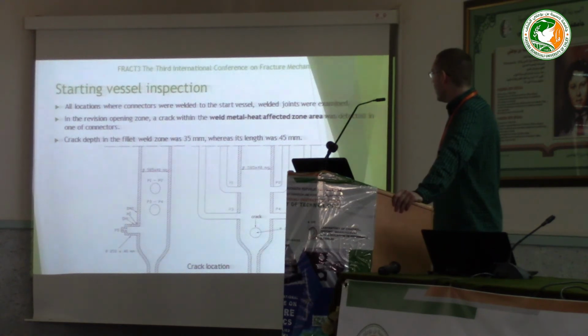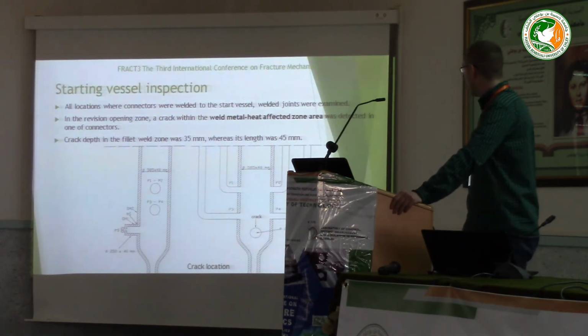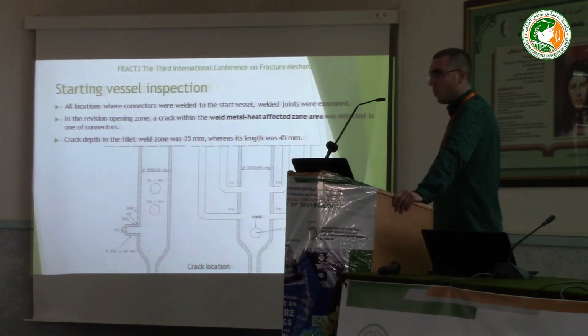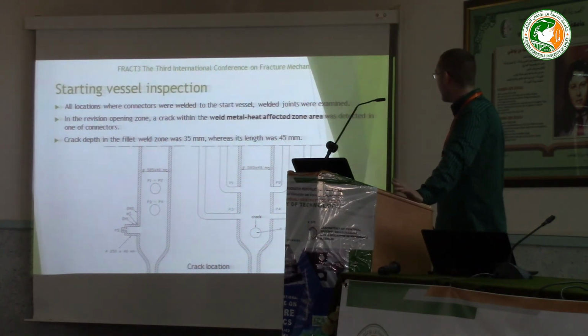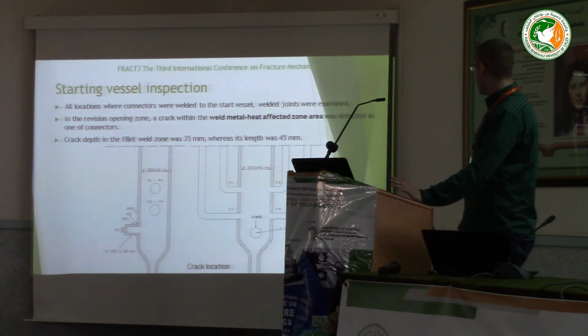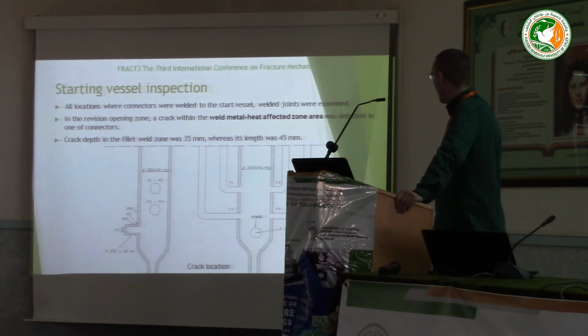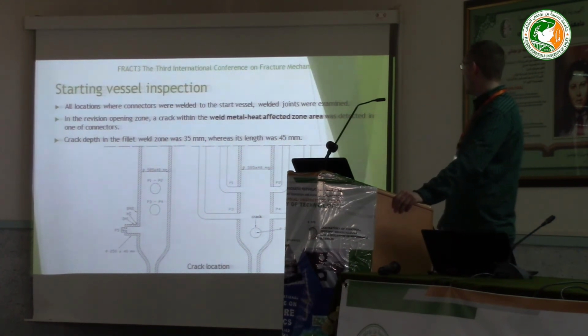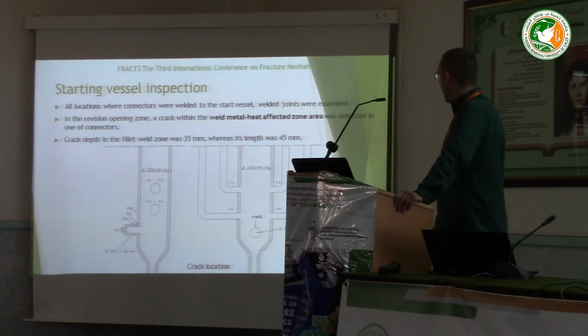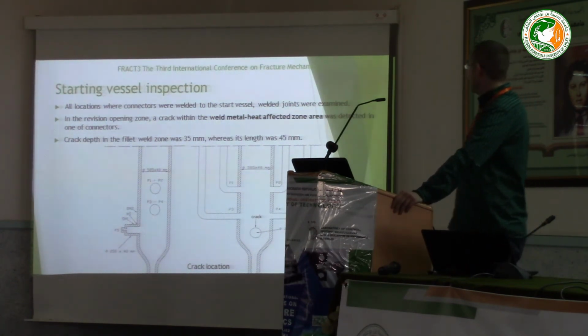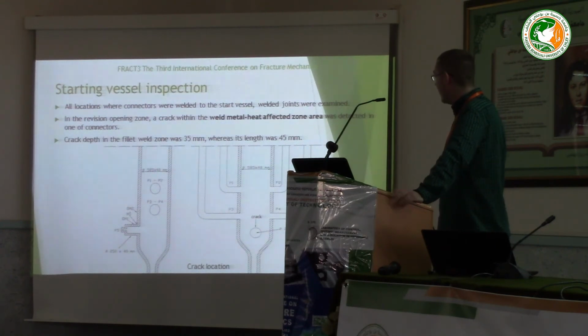As I said, we inspected all welded joints on all five branches that are located on the starting vessel. And during the examination, we discovered one crack. That crack was located on branch number 5. The crack depth in the fillet weld zone was 35 millimeters, and its length was 45 millimeters.